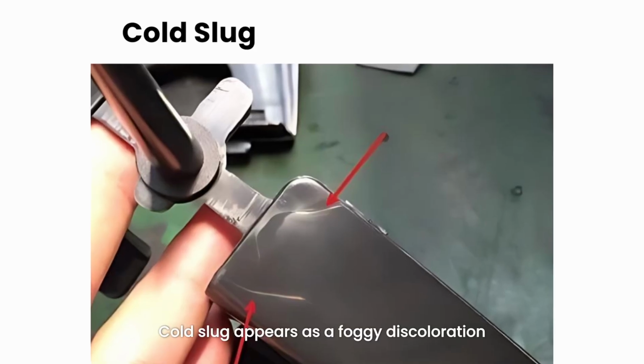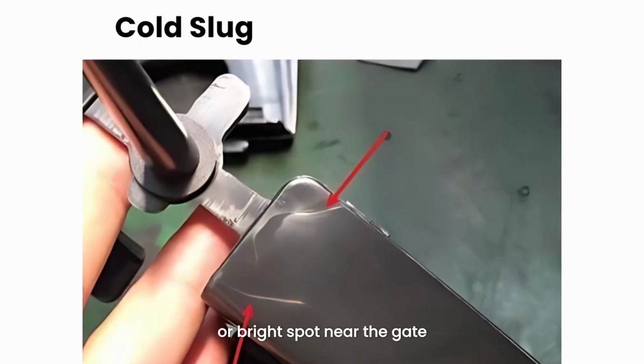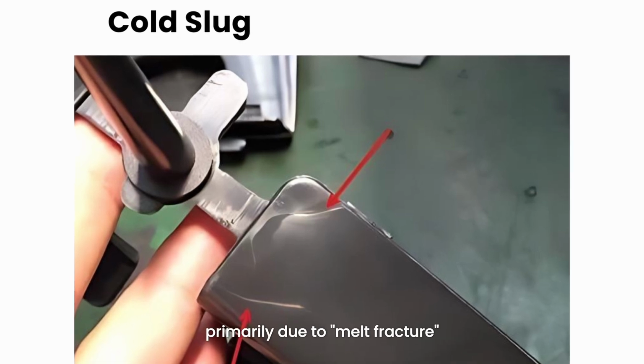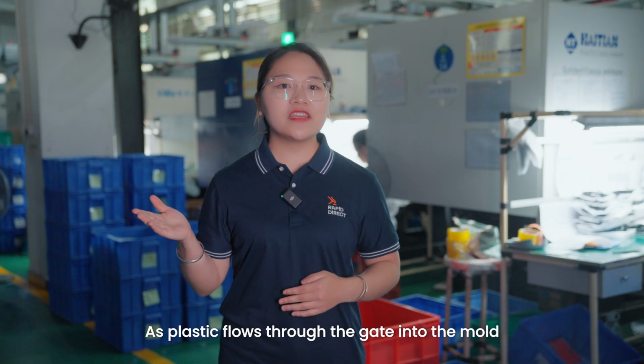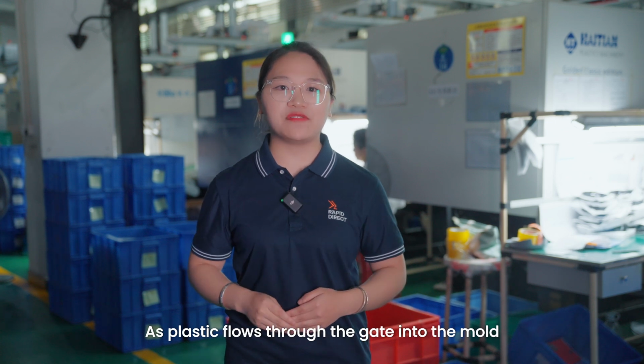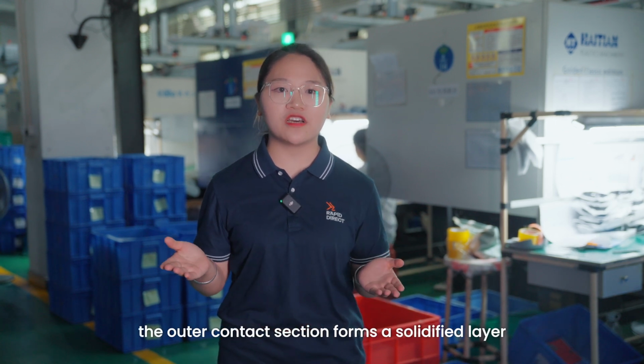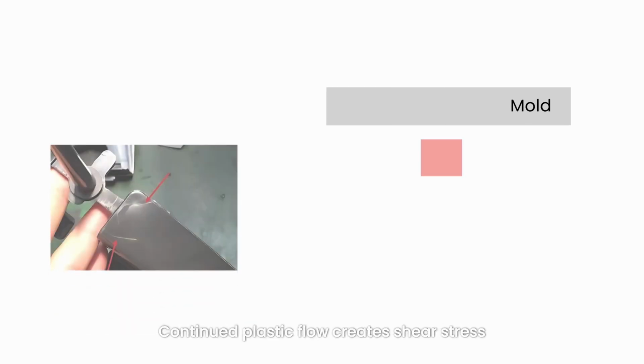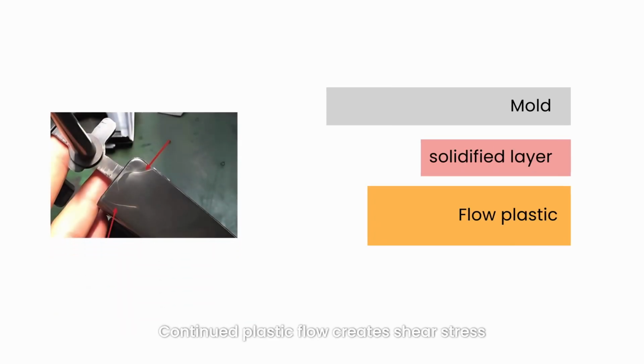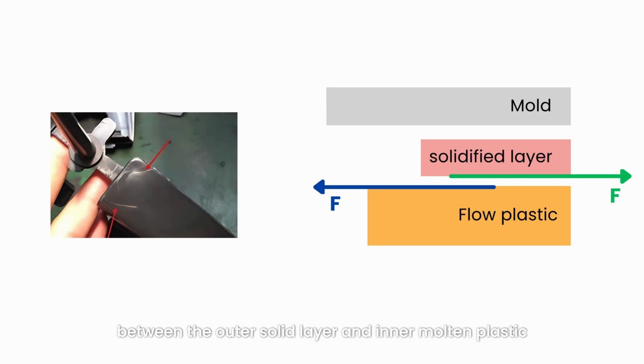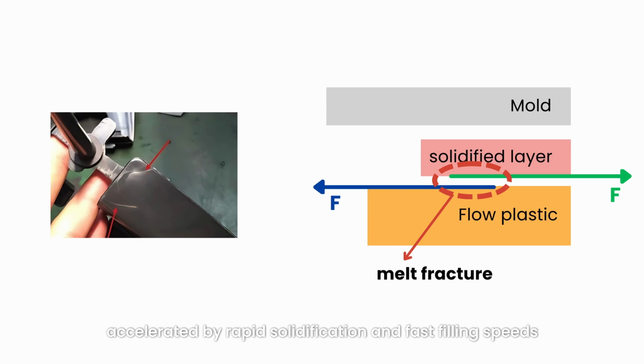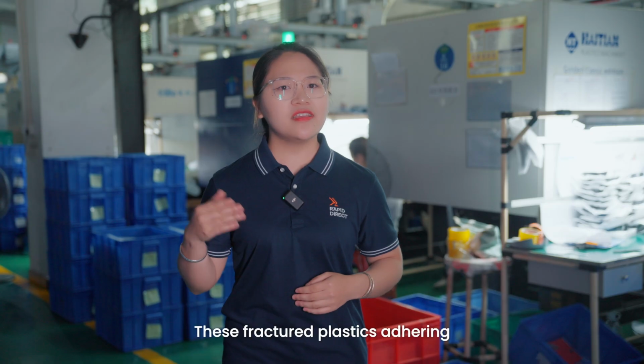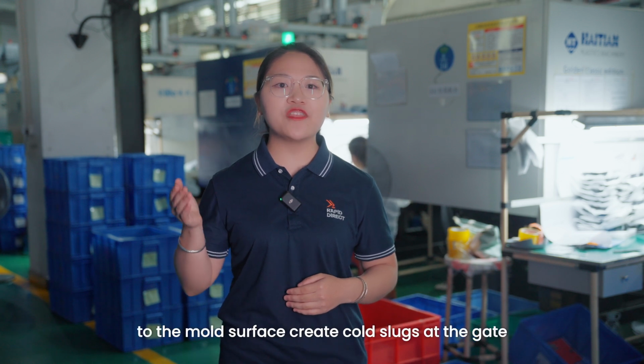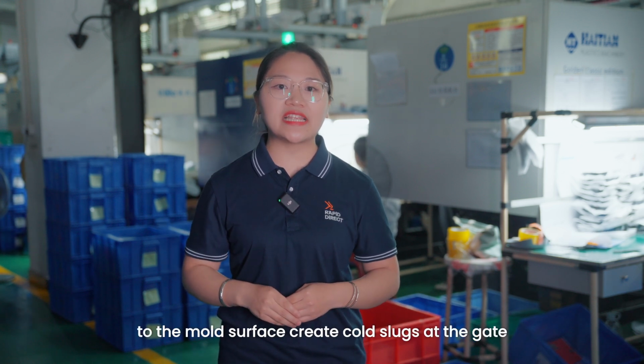Cold slug appears as a foggy discoloration or bright spot near the gate, primarily due to melt fracture. As plastic flows through the gate into the mold, the outer contact section forms a solidified layer. Continued plastic flow creates shear stress between the outer solid layer and the inner molten plastic, accelerated by rapid solidification and fast filling speeds, resulting in melt fracture. These fractured plastics adhering to the mold surface create cold slug at the gate.